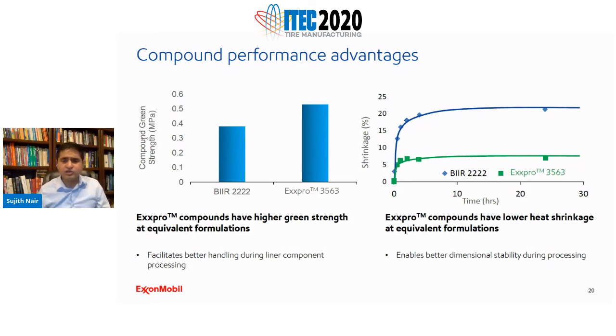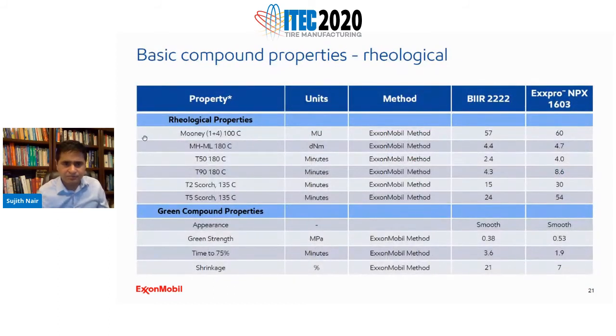The other thing that we observe is when you go into liner sheeting, when you do calendering operations at high temperatures, bromobutyl tends to shrink in the machine direction. This shrinkage is around 20-25%. It shrinks in the machine direction and expands in the width direction. Well, what we have seen with Exxpro is that the shrinkage is extremely small because of the tightness of the polymer and filler, and it prevents any kind of mechanical distortion under heat for the Exxpro polymer. So the shrinkage is much lower, which means that it's got better dimensional stability.